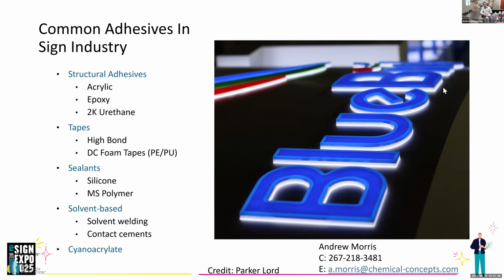So epoxies have what I call linear cure. You basically at 50% of the cure time, you're 50% cured. So if your epoxy is an 8-hour cure, at about 4 hours in, you're about halfway to the ultimate strength. Many acrylics on the market, you can't speak for everybody, but many acrylics on the market really are at 90% strength in the first 2 hours, which is very important for production.